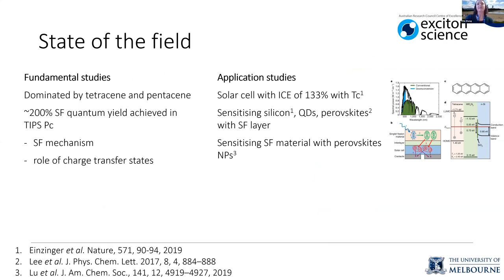So the state of the field at the moment is that most of the singlet fission studies are dominated by tetracene and pentacene. And a part of this is because there's a huge body of research behind it. And the triplet is quite easily observed. It's in a region that's quite easy to see over all of the other things that can be happening, usually the visible range. And I've seen close to 200% efficiency in TIPS pentacene derivatives.